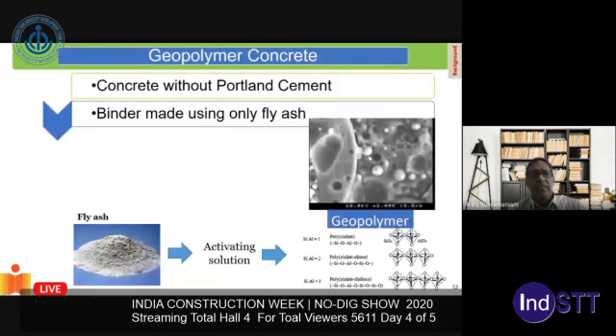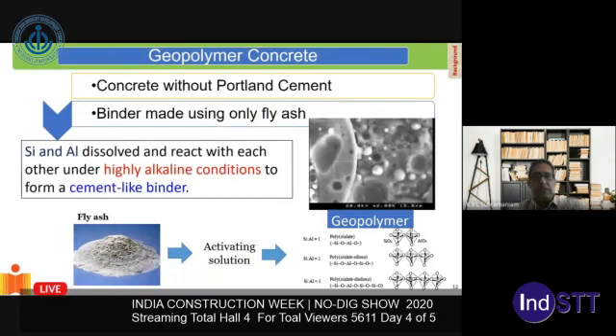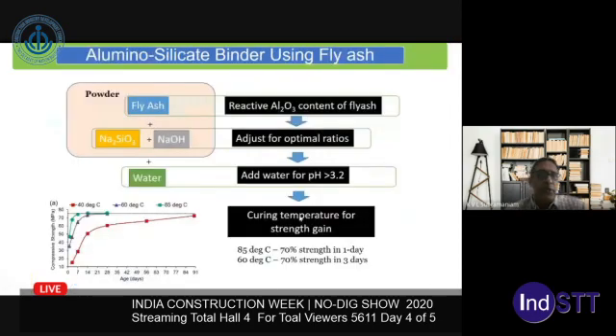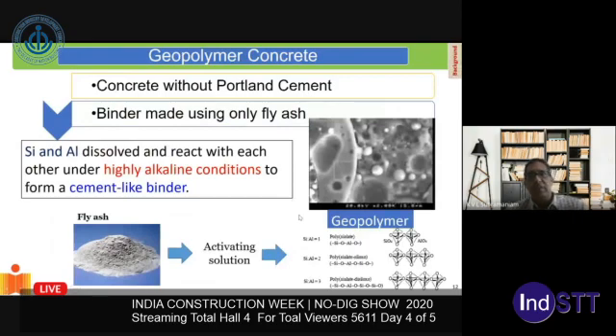So our next step was to look at the possibility of producing geopolymers with this fly ash. For geopolymer production from a given fly ash, it is the reactive silica and the reactive alumina that are important. You take the fly ash, it is activated in an alkaline solution which contains dissolved silica. When you subject it to elevated temperature curing, what you end up with is a geopolymer, which is a densely cross-linked network of silica and alumina, as I've shown here. This geopolymer, if produced from alkali activation of fly ash, particularly low calcium fly ash, tends to have a much higher strength than cement. It is much more durable, and it has very good fire resistance. So it is an ideal material that can be used for construction. The only problem there is, of course, the temperature.